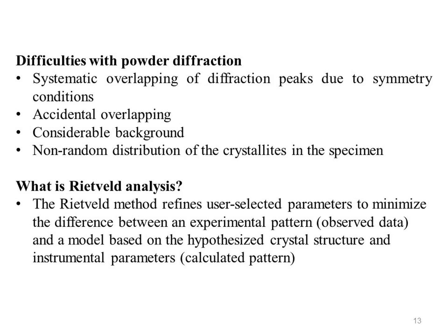Difficulties with powder diffraction: systematic overlapping of diffraction peaks due to symmetry conditions, for example in cubic space groups; accidental overlapping because of limited experimental resolution; considerable background difficult to define with accuracy; non-random distribution of the crystallites in the specimen, generally known as preferred orientation. These are the difficulties which we face during powder diffraction.